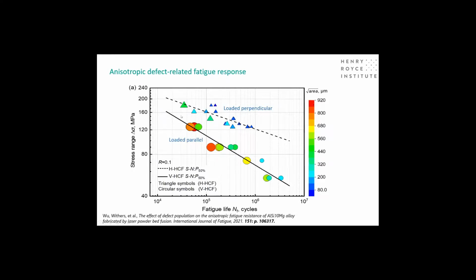And when we plot them color coded, as we've done here, to indicate the projected area of those cracks, Murakami's fracture mechanics predicts that the fatigue strength will be related to the square root of the area of the defects. And you can see when we plot the square root of the area of those defects, the larger defects tend to be in the parallel direction, and in the perpendicular direction, the defects present a smaller area and therefore appear to give a longer fatigue life.